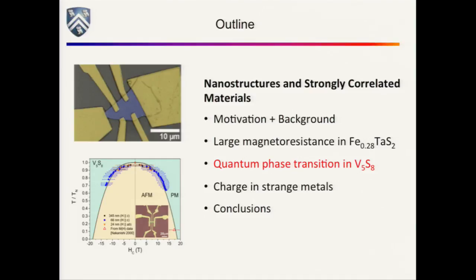That's right. So if you actually want a high coercive field, then what is the advantage of this particular layered material over, say, CMR materials like manganites? Well, the reason you get the magnetoresistance there is that you're actually switching between phases. Whereas here, you're staying in the same thermodynamic phase. You're just manipulating the arrangement of the spin. So they're rather different.